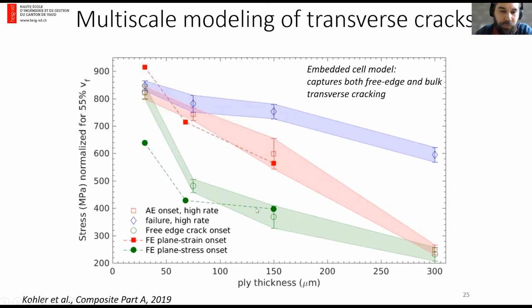So using this model with the plane stress and plane strain assumptions, we could actually replicate properly the onset of free edge cracking and onset of bulk crack propagation here for different ply thicknesses. And this shows somehow that this is the same mechanism, but just the effect of constraint is different at the free edge by suppressing the out of plane stresses, so the out of plane constraints. Free edge cracking appears first because there's less constraint on the plasticity of the matrix at the free edge. So that explains the mechanism from, let's say, its root cause.